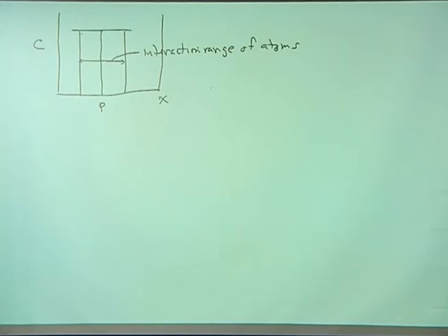And so if you're an atom sitting here, what it says is that unlike this nearest neighbor bond model that we did with a regular solution, you actually can sense the atoms around you a certain distance away that's given by this interaction distance. And so in a crystal, you can have interaction ranges maybe on the order of 4 or 5 lattice parameters. In a polymer, because the size of the chain is so big, these can be really long-range interactions.